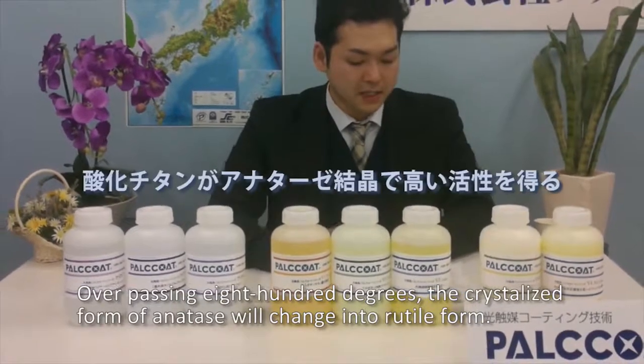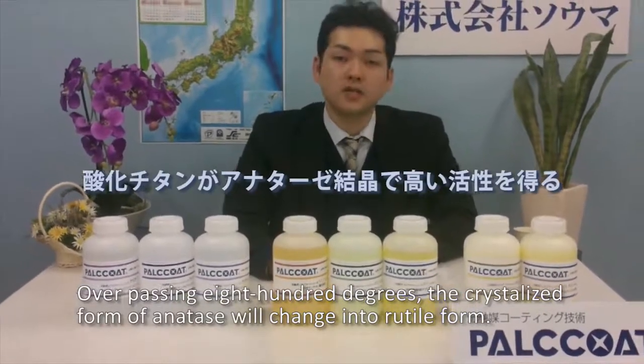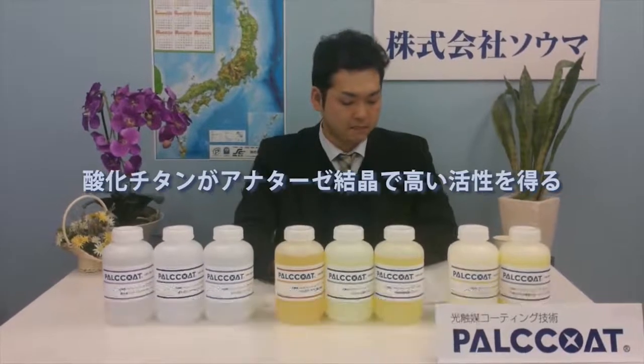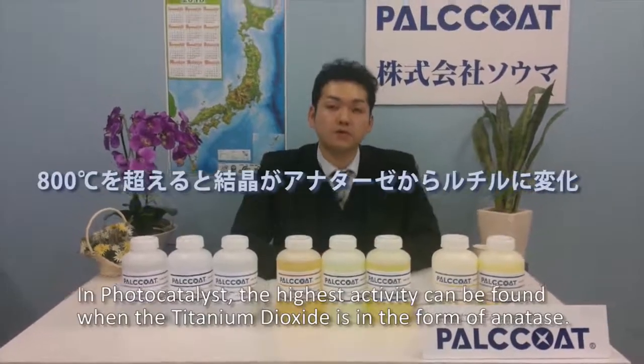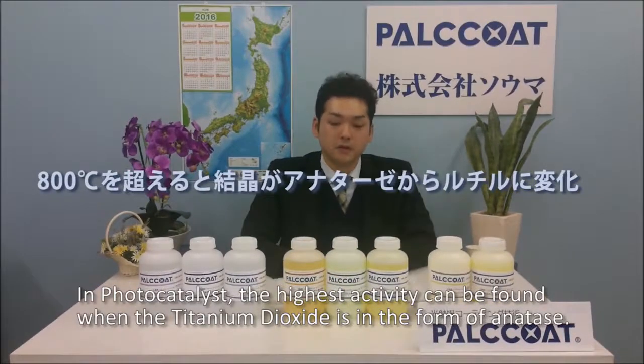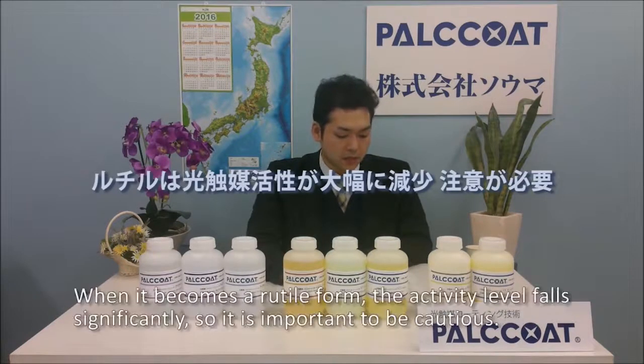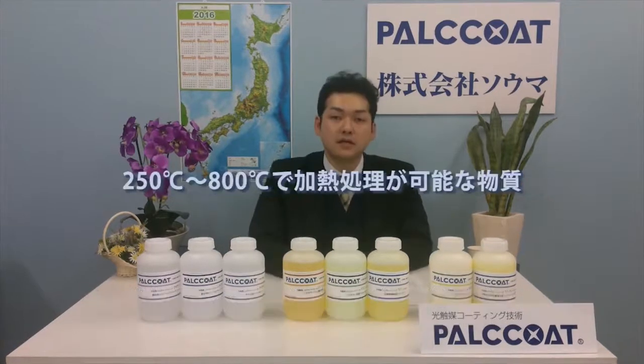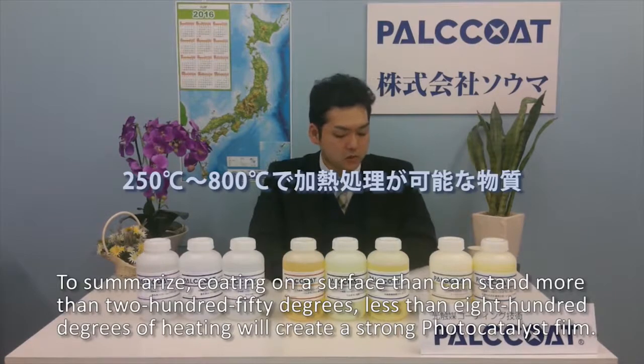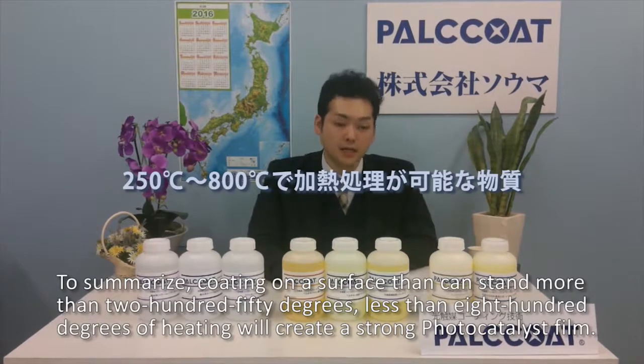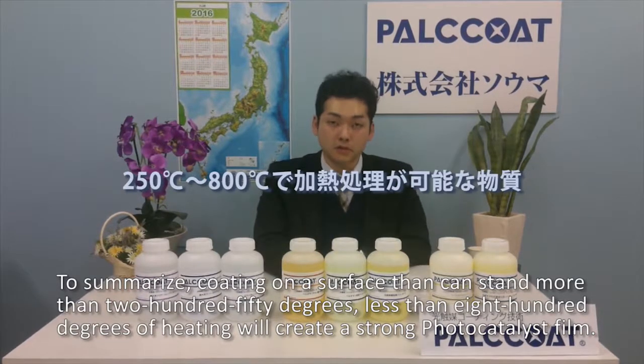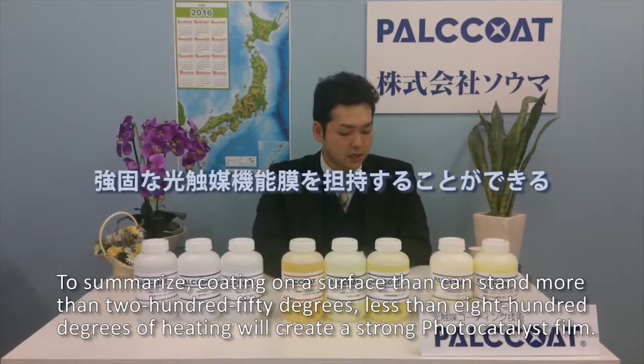Over 800 degrees, the crystallized form of anatase will change into the rutile form. In photocatalysts, high activity can be found when the titanium dioxide is in the form of anatase. When it becomes the rutile form, the activity levels fall significantly, so it is important to be cautious. To summarize, a surface that can stand more than 250 degrees but less than 800 degrees of heating will create a strong photocatalyst film.